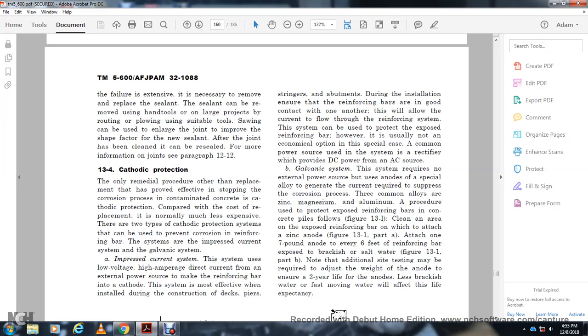The system is most effective when installed during construction of the deck, the pier, with the stringers and abutments during the installation. The internal reinforcement bars in contact with one another will allow the current to flow through the reinforcement steel. The system can be used to protect exposed reinforcement bar, however, it is usually not an economical option. It has a common power source with a rectifier, which provides DC power from the AC source. The galvanic system uses no external power, but a special alloy to generate the current required to suppress the corrosion process.